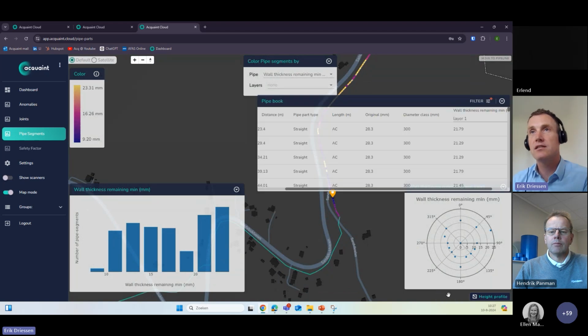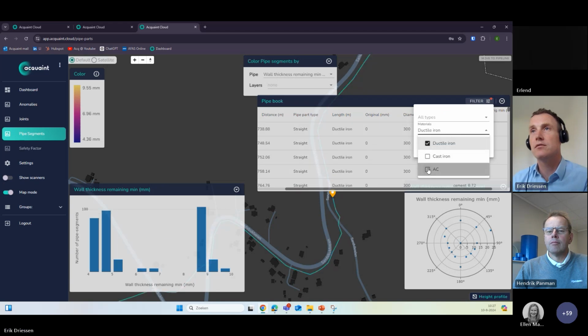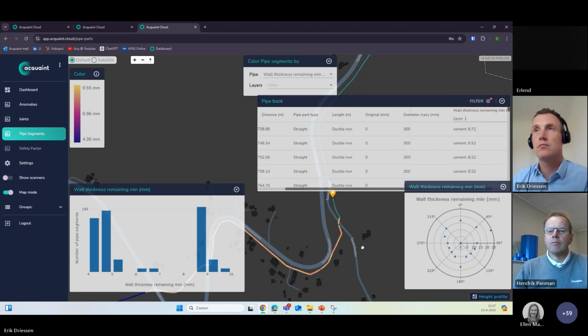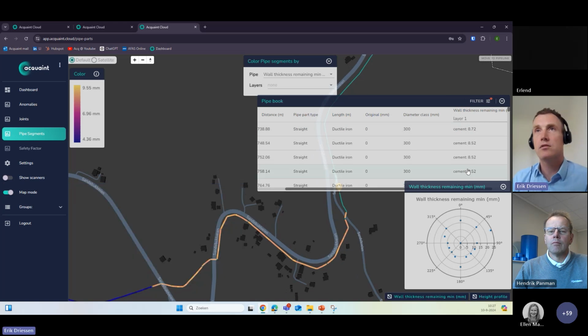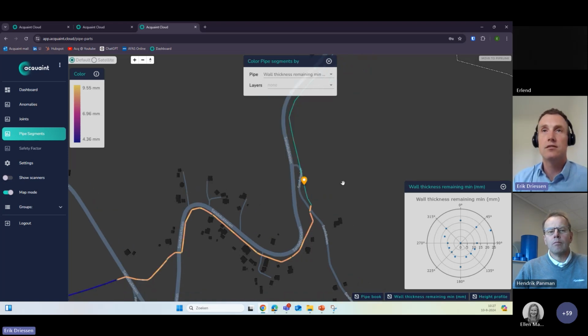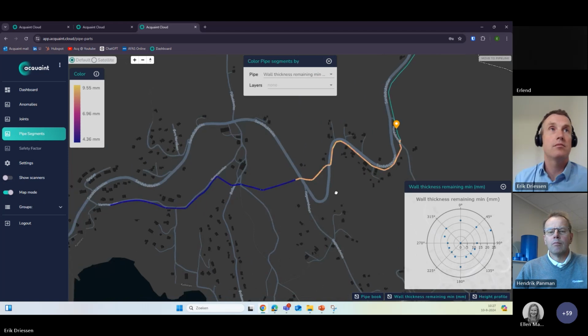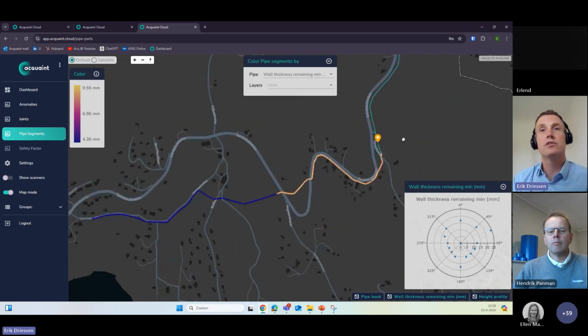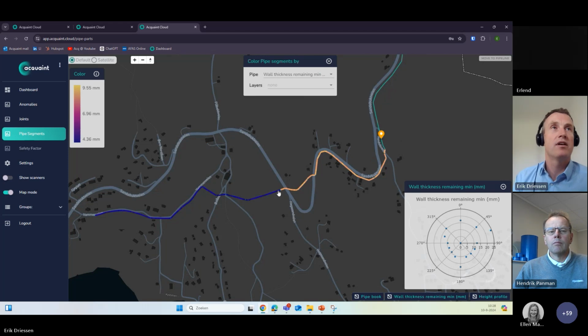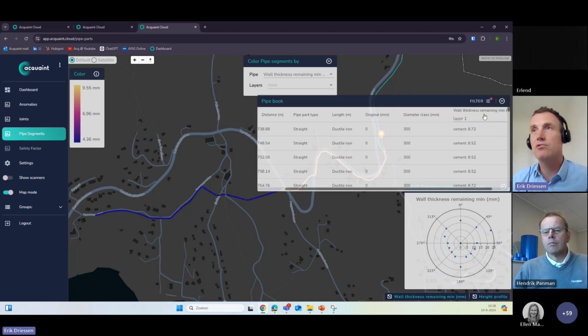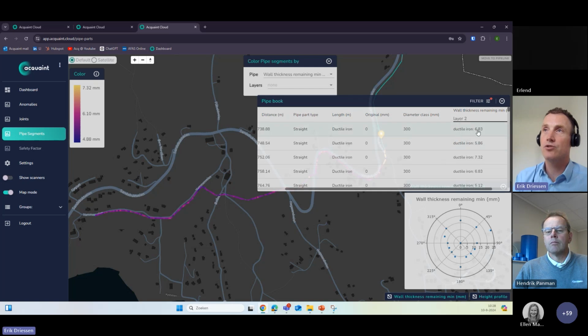Let me open the pipe book again and go to the ductile iron. And let me minimize this one. So we're still looking at the minimum wall thickness. So this is the ductile iron pipeline. And you see clearly two colors because in the pipe book, I selected the first layer. The first layer is cement, the second layer is the ductile iron, and the third layer is a combination of both.